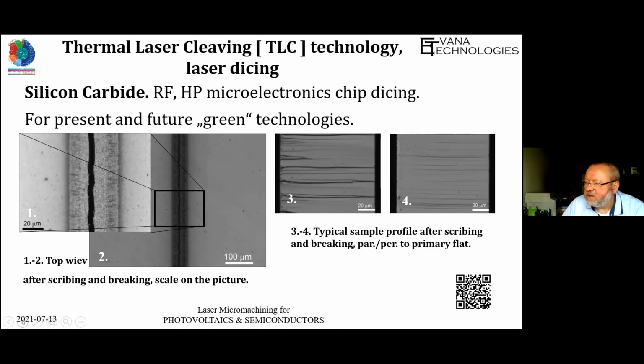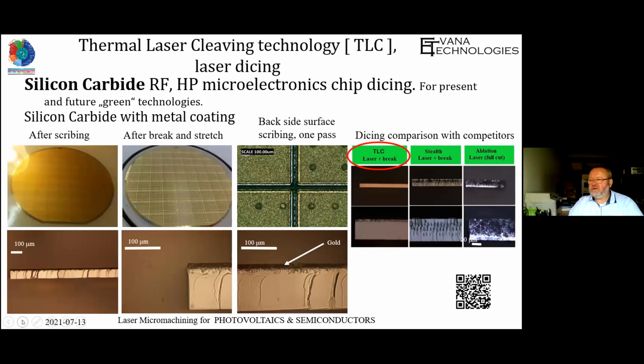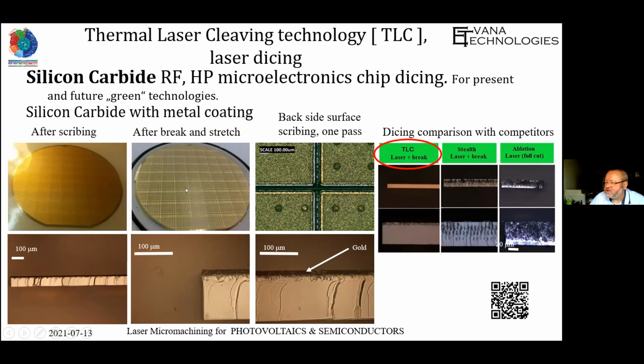Here is another sample for which we also developed dicing technology. When the material is coated by gold film, we make this in one pass, in one scribing dicing process, at 300 millimeters per second, and you can see here the sample after scribing and the sample after breaking and stretching. View at micro scale, you can see here the street view and some comparison with stealth dicing and ablation laser processing.